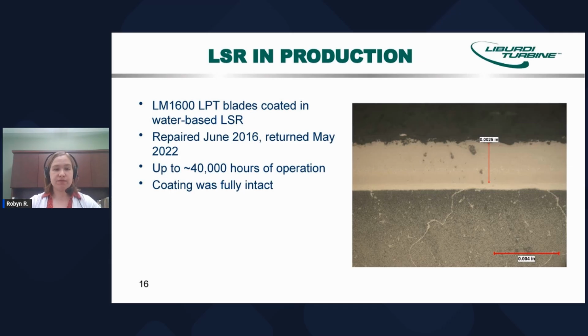One of the helpful things for our process and for our continued developments and improvements is the ability to see our own coating returned to us after service. For example, we first implemented the water-based LSR on parts in 2016, and since then have consistently gotten back the same parts at their next repair cycle and been able to see how they fare under service. This particular blade, the LM1600 LPT, we coated in our water-based LSR back in June of 2016, and the same set returned to us in May of 2022, having undergone approximately 40,000 hours of operation.